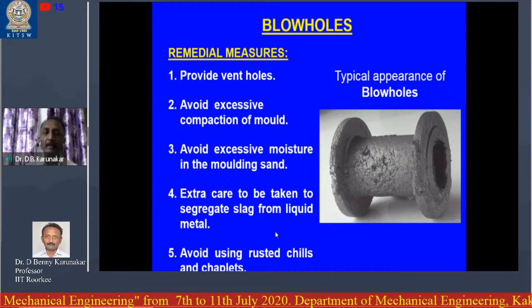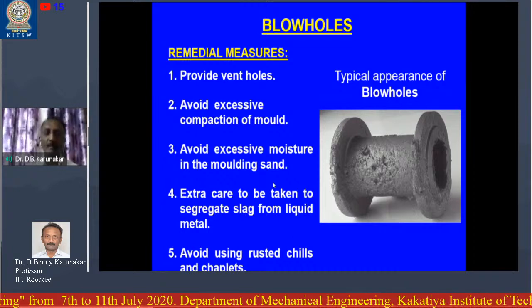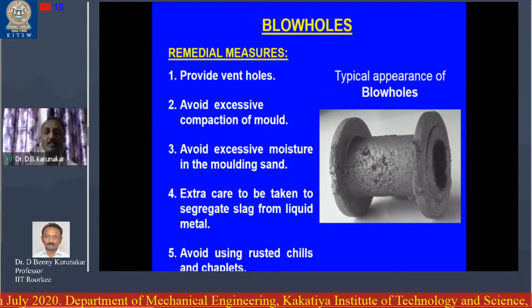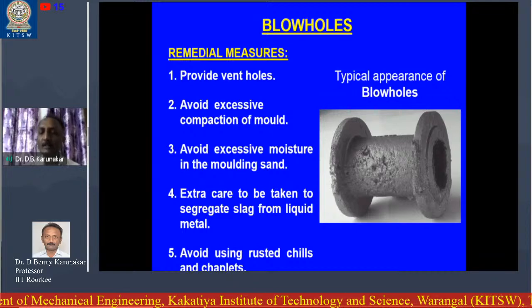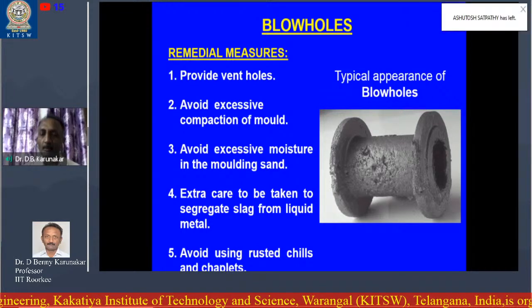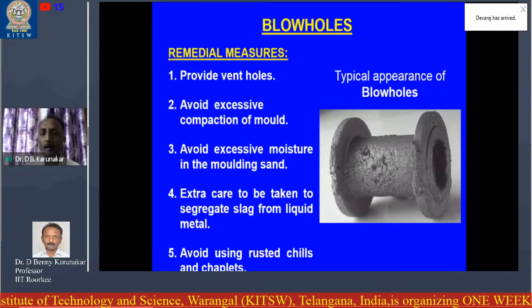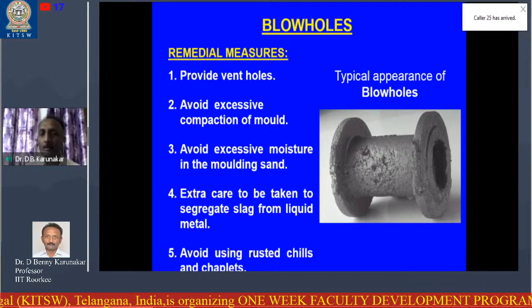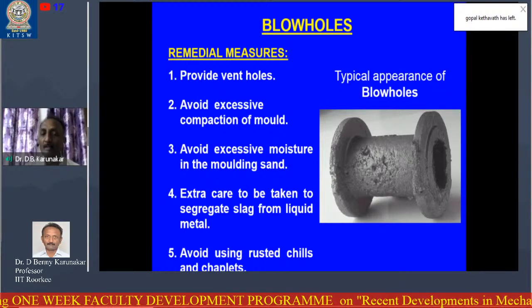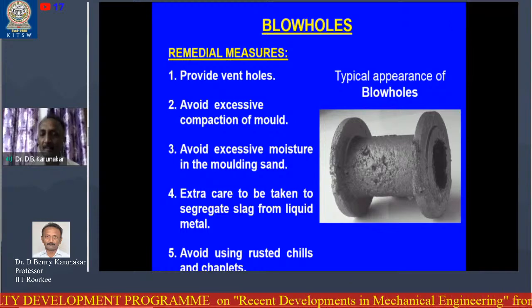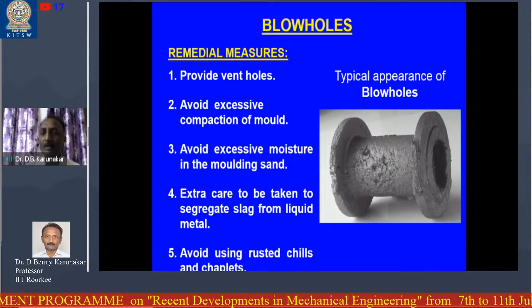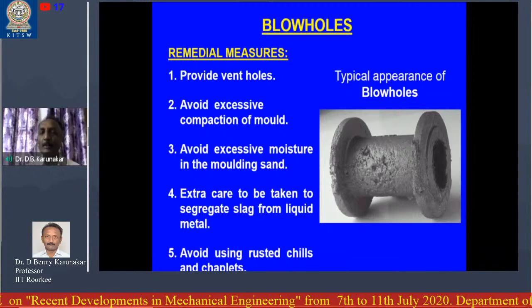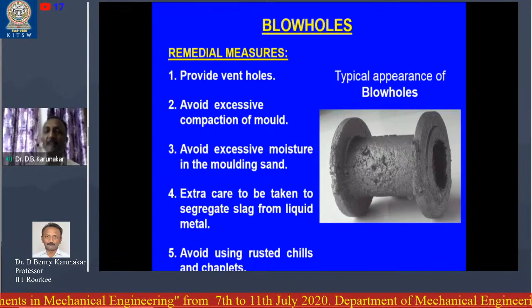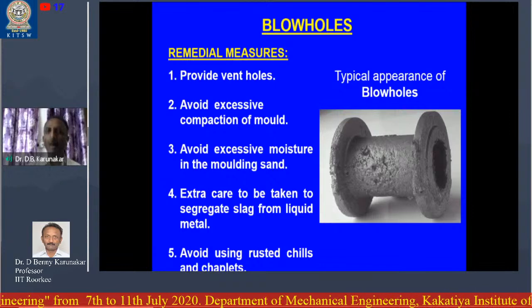Extra care should be taken to segregate the slag from the liquid metal and avoid using rusted chills and chaplets. We use chills and chaplets in the casting process. Chills enable directional solidification, and chaplets are used for supporting the cores. Sometimes these get rusted, meaning iron oxide forms. Once there is iron oxide, there is an oxygen component that reacts with the molten metal and forms carbon monoxide.